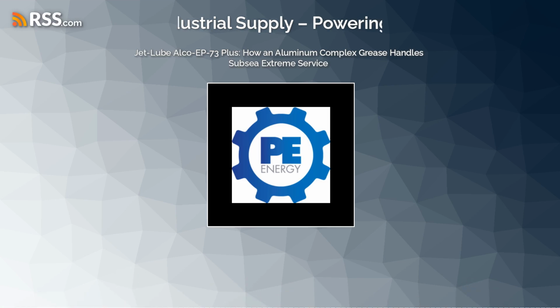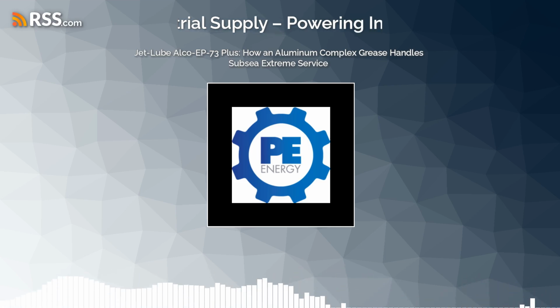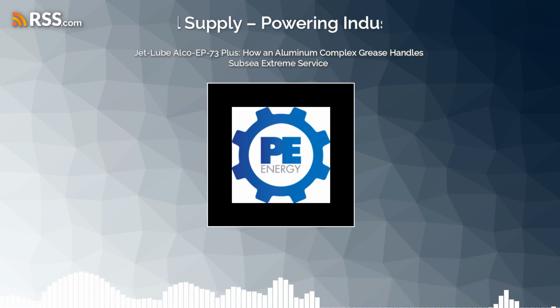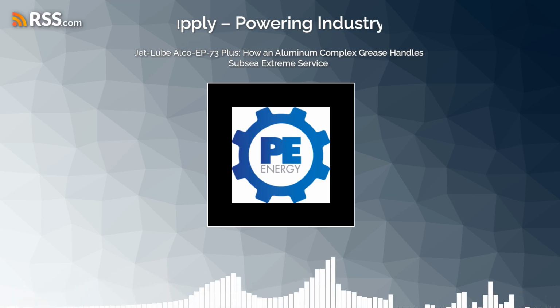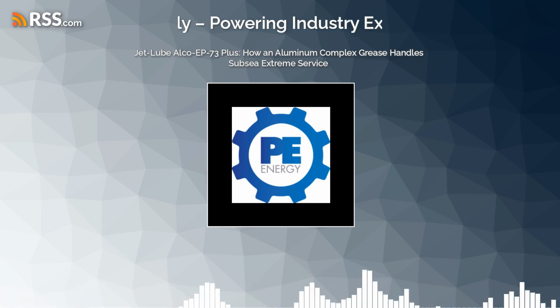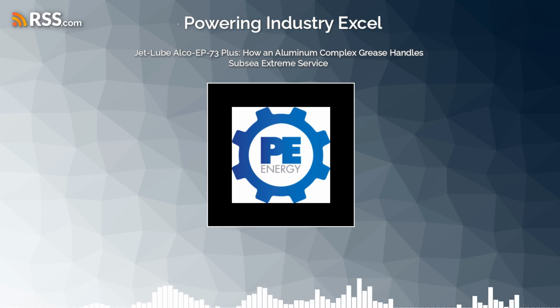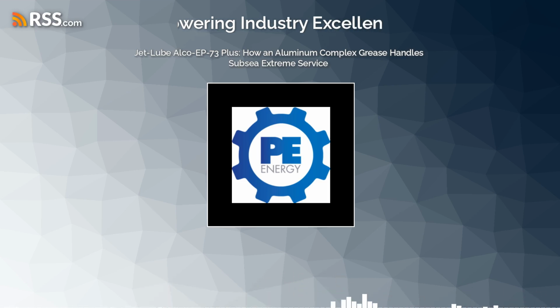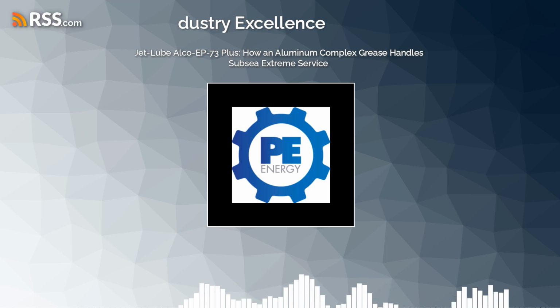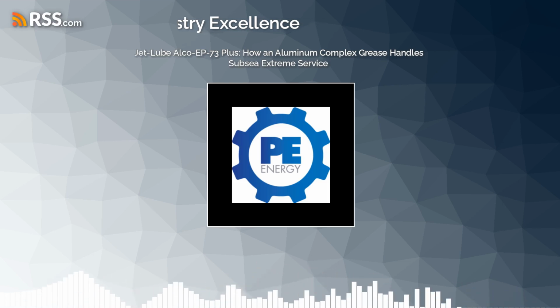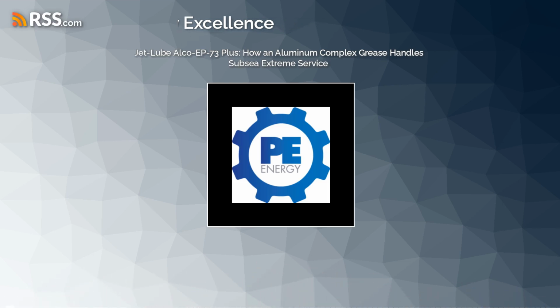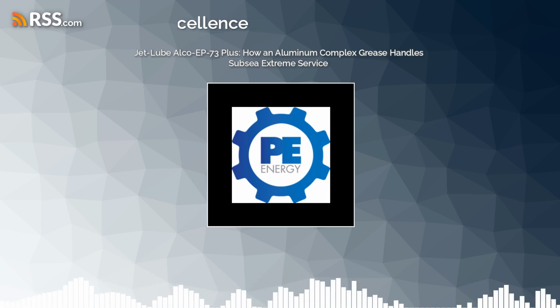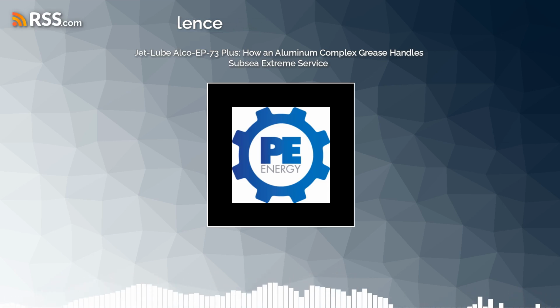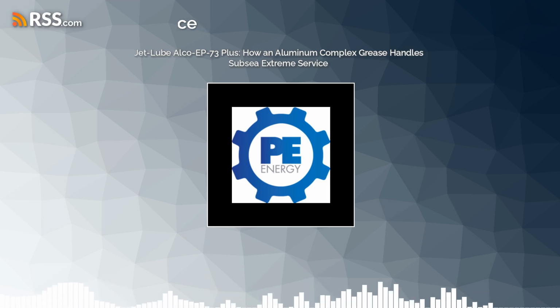It's highly inert. And they verify that lack of reactivity with the copper strip corrosion test, which the sheet lists as a 1A rating. I really wanted to ask about that. Why copper? Heavy industrial machinery and deep-sea rigs are made of steel or titanium, not copper. It's a great question. Copper is incredibly soft and highly reactive, particularly to sulfur. And sulfur is in the grease. Sulfur is a very common element in extreme pressure additives. If a lubricant has unstable or highly corrosive additives, it will rapidly etch, pit, or turn a copper strip black.